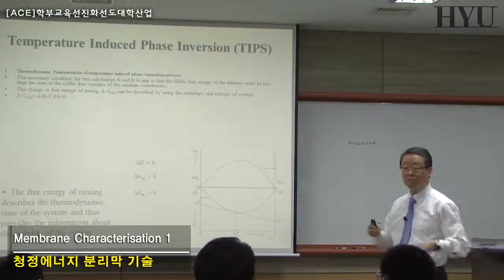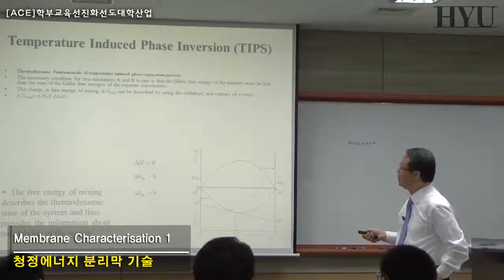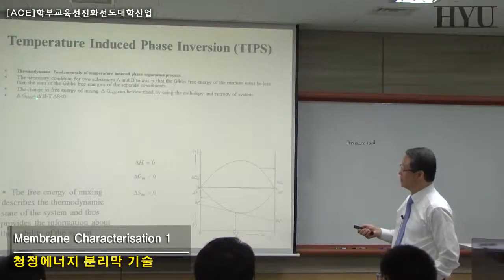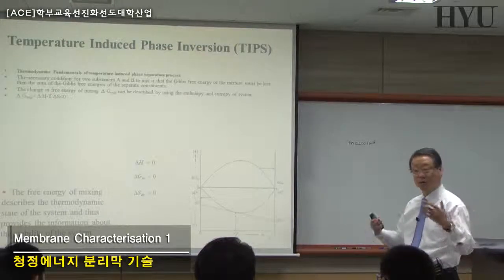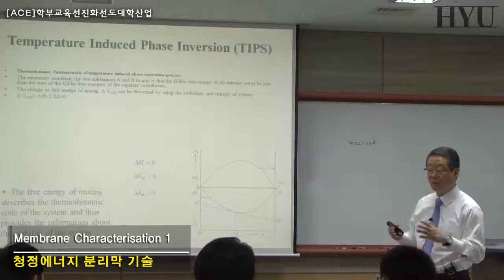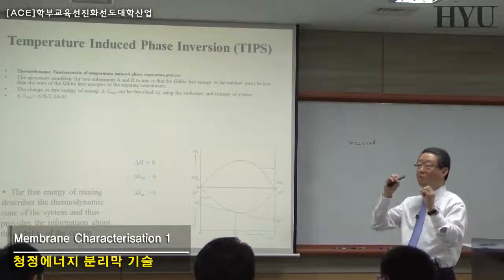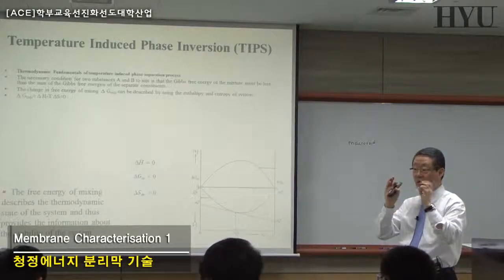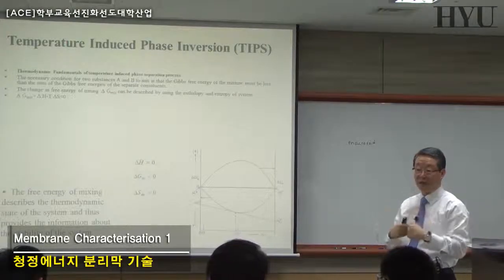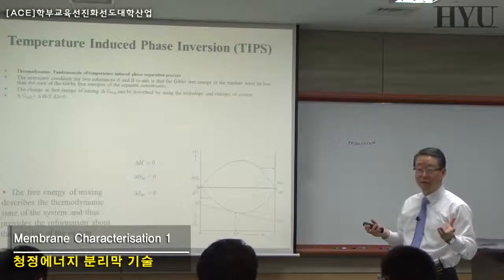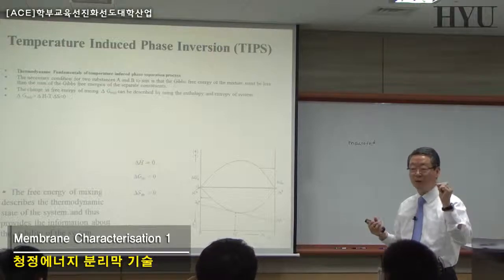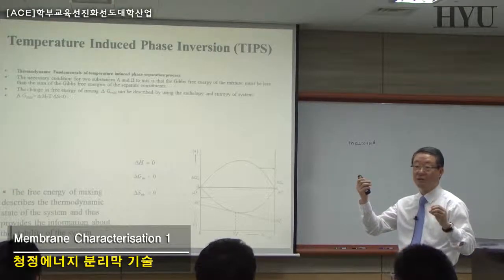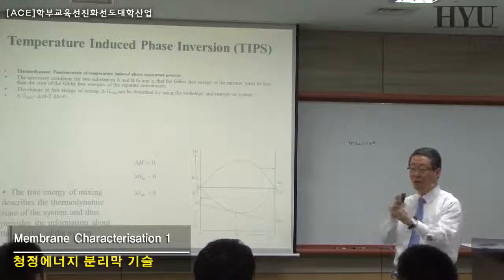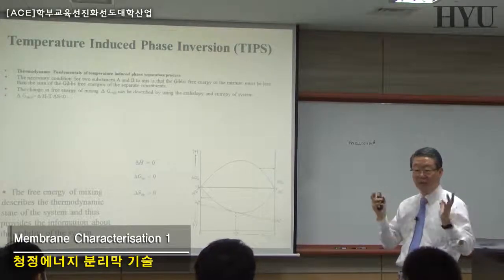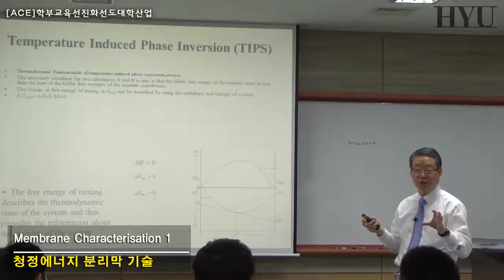And the first term, of course, should be negative, right? So in that case, you mix your polymer into your good solvent. Okay, good solvent is the one where the polymer-solvent interaction is much larger, so that you have a negative delta H. Poor solvent is the one where polymer-polymer interaction and solvent-solvent interaction is much stronger than polymer-solvent interaction. So in that case, poor solvent has a positive delta H.